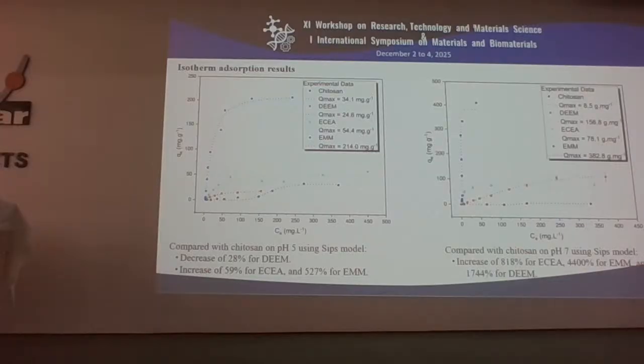For pH 7, we have a really high improvement. For chitosan, we have a maximum absorption of 8.5 milligrams per gram. But for the EMM, we have a maximum absorption of 382 milligrams per gram, which showed us 4,400% of improvement with this modification. The other one has improved as well. The DEEM is now better. We don't know why yet. We're studying it.